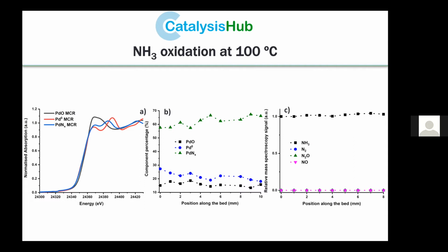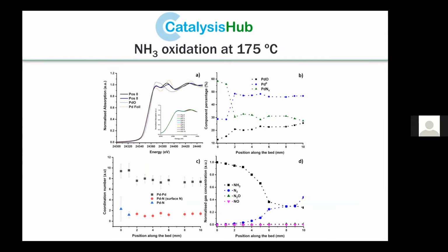When applying this analysis to the XANES data I showed you before, it's clear that palladium nitride is the majority phase. However, it's possible to identify minor amounts of both palladium oxide and palladium metal. Again, this proportion is consistent across the bed. However, as we increase the temperature to 175 degrees, which is prior to full conversion of ammonia, there's a clear spatial variance in the palladium speciation across the bed, as evident by both the XANES MCR and the EXAFS, which you can see in A and B, along with the spatial variation in the conversion of ammonia, C.